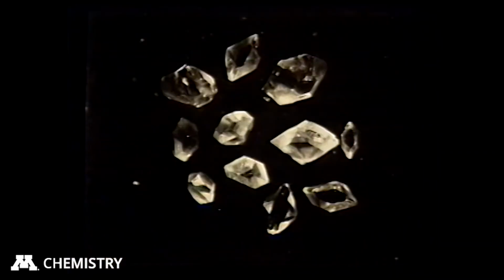Can you tell which one is which by the shape? And the other interesting thing here is that several of these polymorphs interconvert under different conditions. Even more interestingly, this first polymorph here, which was grown by slow evaporation from methanol, contains half of the molecules neutral and half of the molecules zwitterionic in the same crystal. And if you think about the process of molecules going from solution into the solid state, think about some situation under which proton transfer is favored, and you'd get zwitterions. But it would surely have to be a very different set of conditions where the proton transfer is not favored.